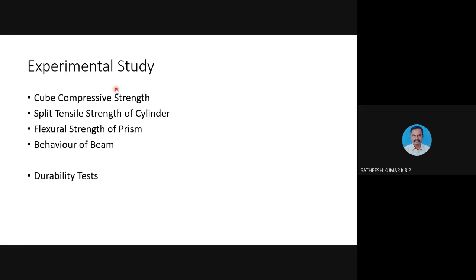We were trying to achieve M20 concrete, or a cube compressive strength of 20 megapascals. The low molar solutions, namely 6 and 8 molar, did not result in a very good compressive strength. The values are not anywhere near 20 megapascals. But what we observed is that the solutions with relatively higher molarity, 10 molar, 12 molar, or 14 molar, all these mixes had a very good compressive strength, a little more than 20 megapascals. To talk about the split tensile strength of the concrete,